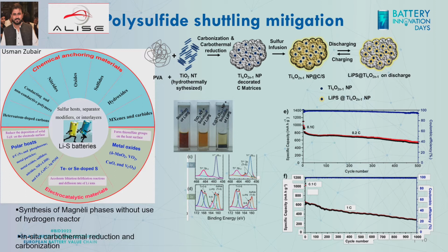These particles can really block the polysulfides that are forming. After getting the host material, sulfur was melted inside the structure. Let's remember that the melting point of sulfur is quite low, so it's quite easy to prepare in porous systems. If you have a porous matrix, it's quite easy to make sulfur move inside. And you can see very easily in this figure that these are solutions containing polysulfides, and with this kind of material, the color of the solution becomes lighter because of the trapping of polysulfide. You can also reach 1,000 cycles at 1C with this kind of material.